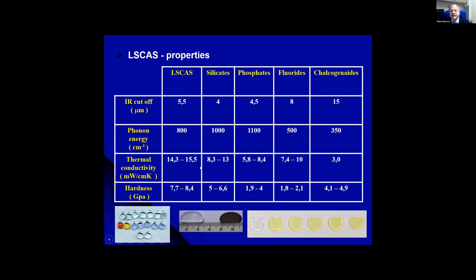So this glass has the highest thermal conductivity that can be found in glasses, and also hardness, so it's a very good glass. If you see here, there are some photos of some dopings, and you can observe that all these materials are made of high purity compounds, oxides, and the optical quality you can see here is quite good. We have used this glass also to make lasers, but in this presentation, I'm going to focus only on white lighting and solar stuff.